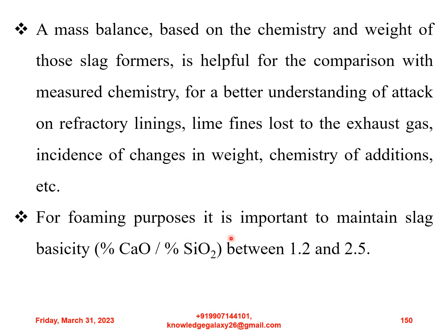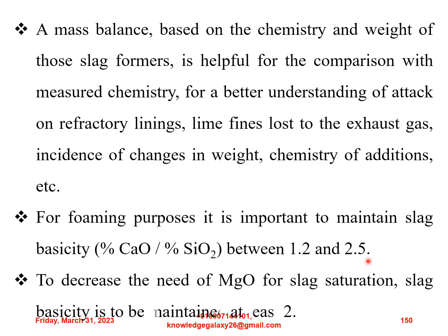For foaming purposes, it is important to maintain slag basicity, that is percentage of CaO divided by percentage of SiO2, between 1.2 to 2.5. To decrease the need of MgO for slag saturation, slag basicity is to be maintained at least at 2.